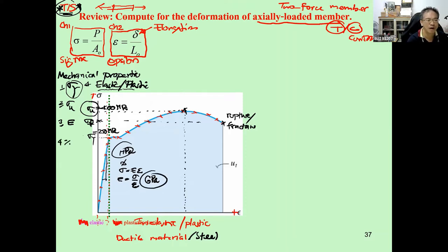And the last one, you've got to find the percent elongation. Some people say you may use the epsilon sub f, but practically, it isn't epsilon sub f, since the percent elongation comes from the equation that you know: L sub f minus L sub o, divided by L sub o, times 100. But the L sub f is calculated from the specimen that has returned by the elastic recovery. So it's going to be very close to, but not exactly the same. Okay.